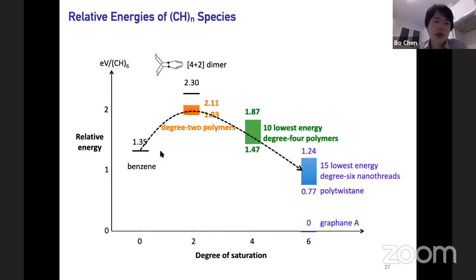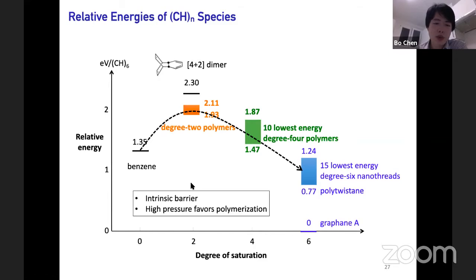And this leads to an intrinsic barrier for the transformation from benzene to degree six nanothread. And that's why pressure is needed to overcome this barrier. Another thing I want to point out in this slide is that once the degree four or degree six nanothreads are formed, it's unlikely they will revert back to benzene because of this barrier.